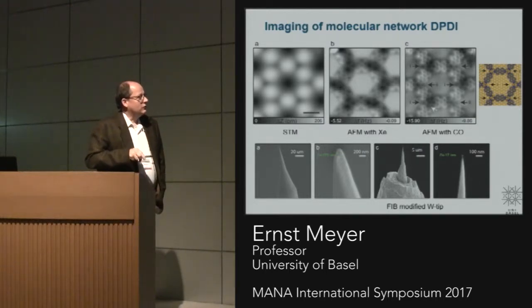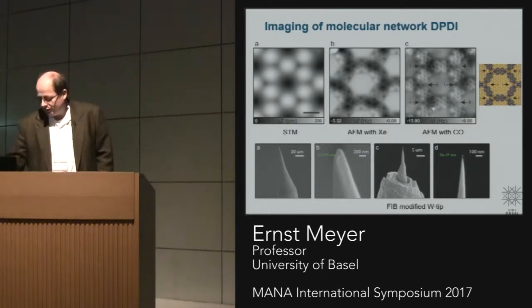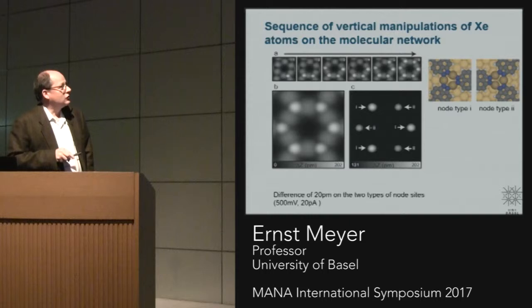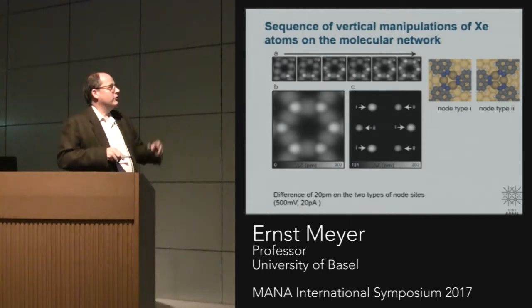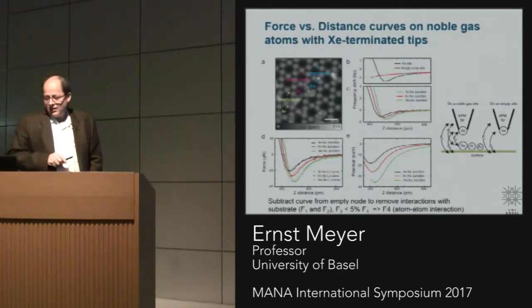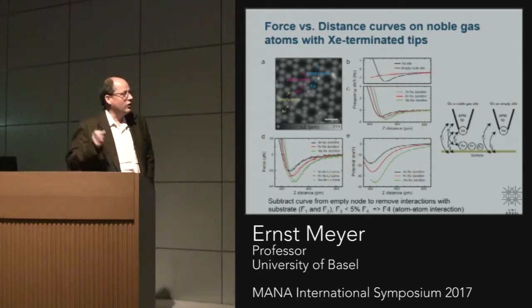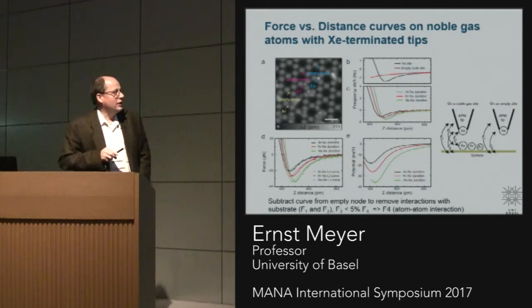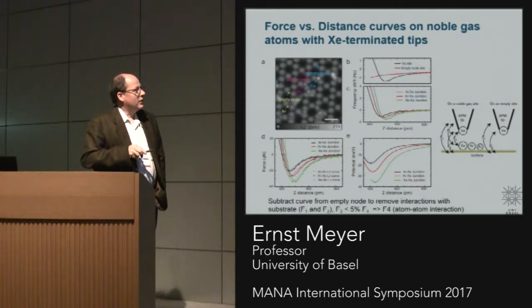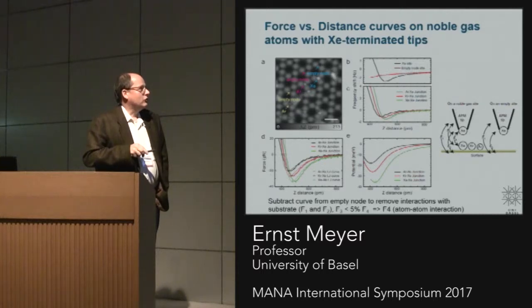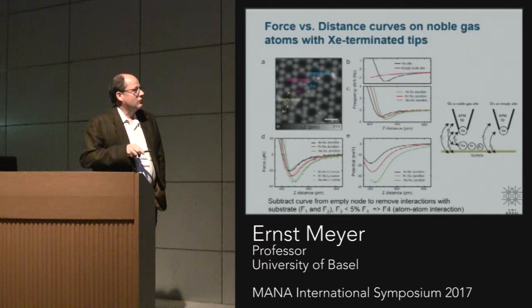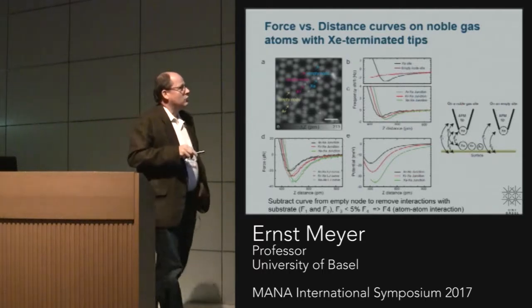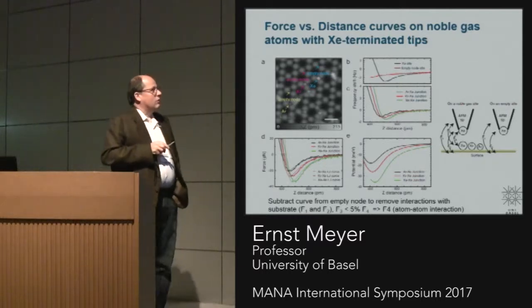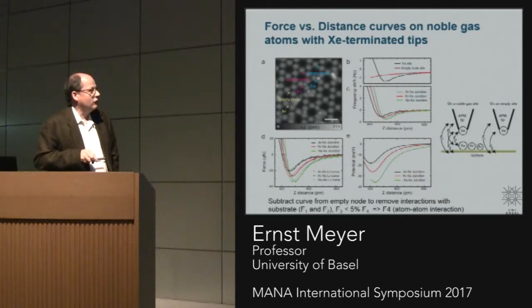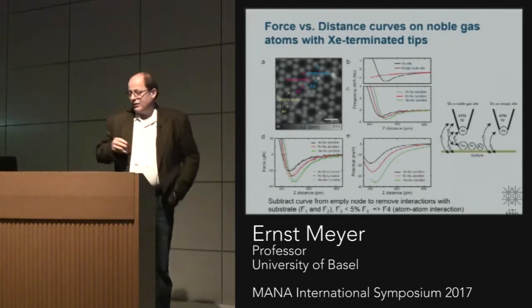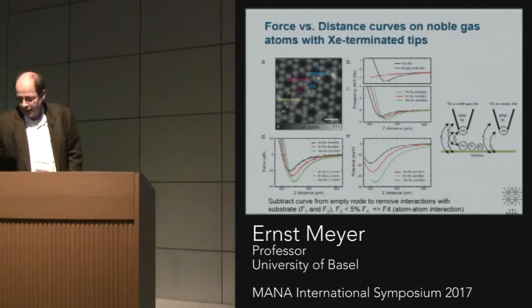Also, what turned out to be important is that you use this focused ion beam modified tip to reduce the long-range forces. Now you can fill these nodes. There are two types of nodes. Maybe it's a bit of detail, but the main thing in the end is you measure once with a node filled with xenon and once without, and then you take the difference, empty node versus xenon. You can also do it with krypton and argon, and you see that the largest is for xenon, the larger atom, then krypton, and then argon. And you can then finally calculate forces and also the potential energy, that you can now compare with typical pair potentials as we know them.